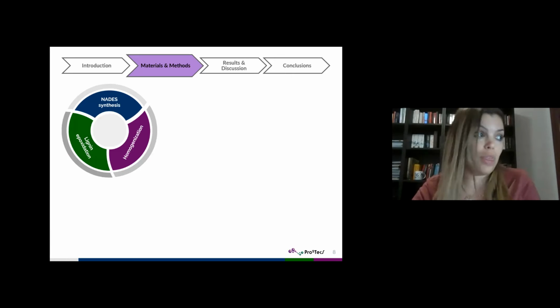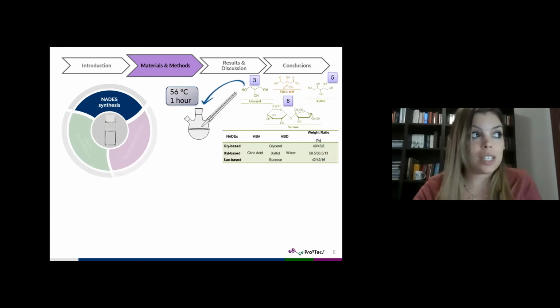It is divided in 3 steps. Firstly, the synthesis of NADES was carried out by mixing all the components at 56 degrees Celsius for 1 hour. In this case, 3 hydrogen bond donor compounds were selected in this work. I mean glycerol, xylitol, and sucrose, containing a different number of hydroxyl groups in their molecular structure, and using citric acid as hydrogen bond acceptor.